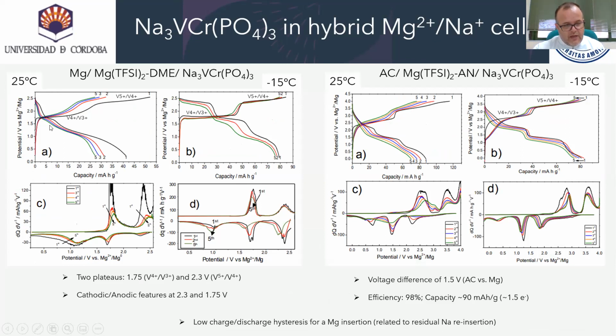There are two plateaus at 1.7 and 2.3 due to vanadium 4, vanadium 3 and vanadium 5, vanadium 4. Here at 25 degrees and at -15 degrees. Also, there are cathodic anodic features at 2.3 and 1.75 volts. Also, there is a third plateau here at 1.2 volts that is due to the magnesium insertion.